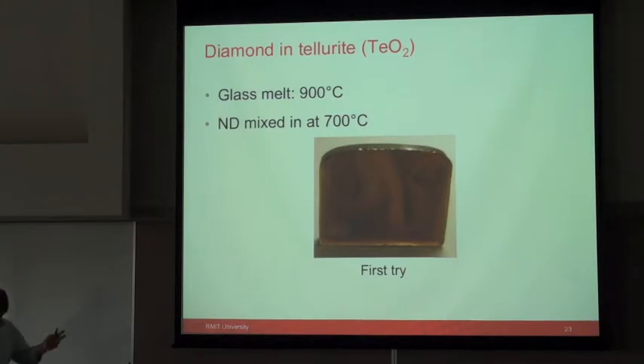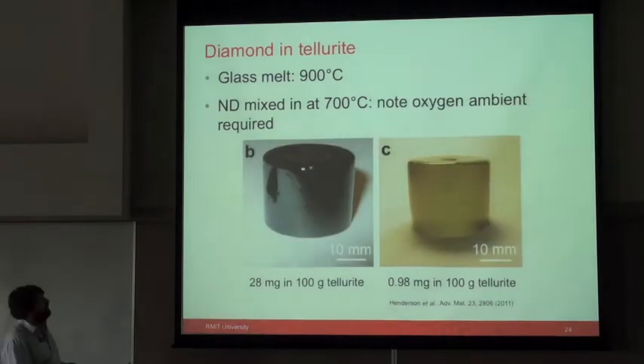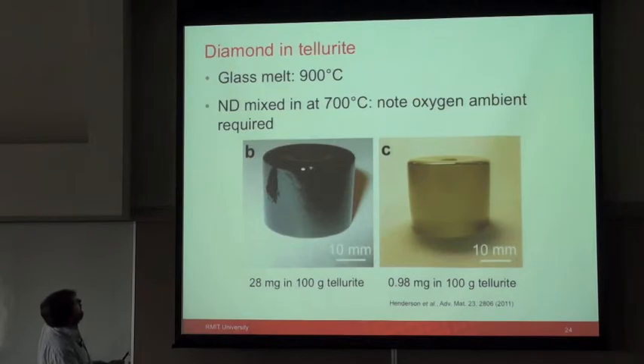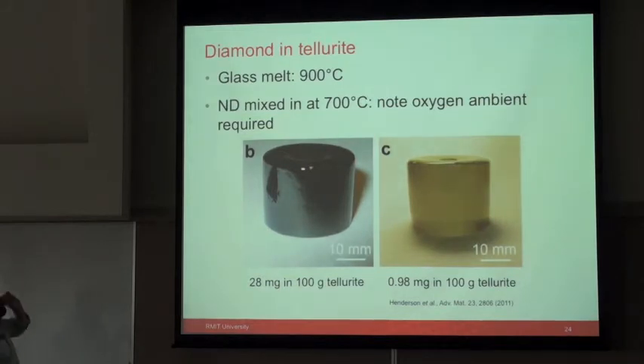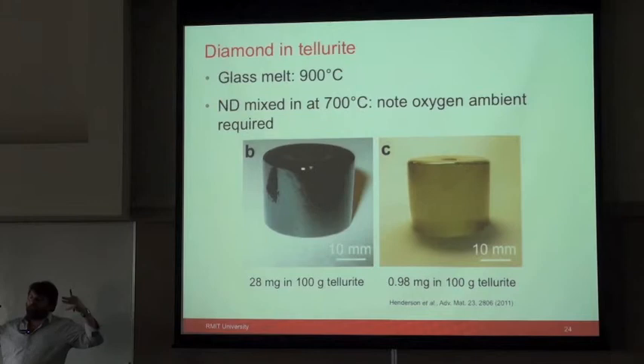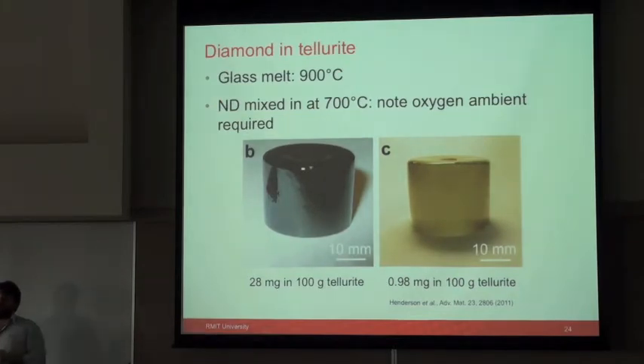And so the first try, that wasn't very good. The second try, we started to get much better. These are some billets, and you can see that by changing the concentration of the diamond in the tellurite, we're improving the quality of the glass. This is a good time to point out one of the big problems with tellurite as a glass is that it requires an oxygen ambient. And this tends to burn the nanodiamonds, which means that you need to work fairly quickly, and you want to work at the lowest temperature you can get. Typically, nanodiamonds burn in oxygen at about 650 degrees.